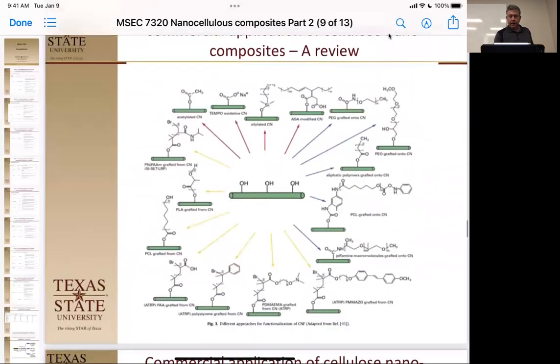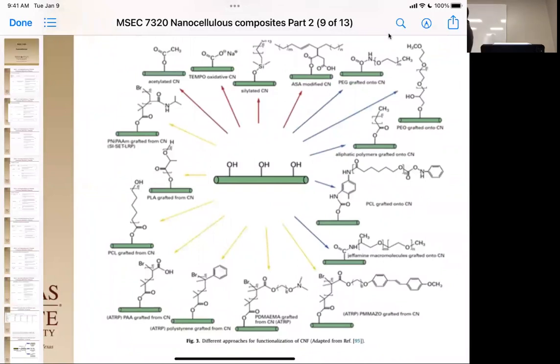All right. Now, the other cool thing is carbon nanotubes are hard to functionalize. We have to heat them in acid and do a little bit of functionalization. Graphene, if we over-functionalize it, turns into graphene oxide. In the case of our nanocrystals or nanofibrils, they are inherently built to have alcohol groups all over the outside. As soon as you isolate them, they are functionalized. Depending on what you want to do, you can do a wide variety of things, like compatibilizing with ethers or aromatics. In fact, we'd want something like this if you wanted to mix graphene in with it. Why? Pi stacking, exactly. And this one's nice and flat too, so this is going to help compatibilize graphene into your system.